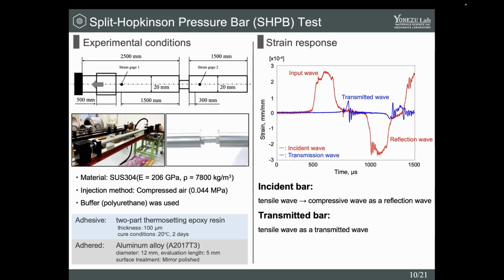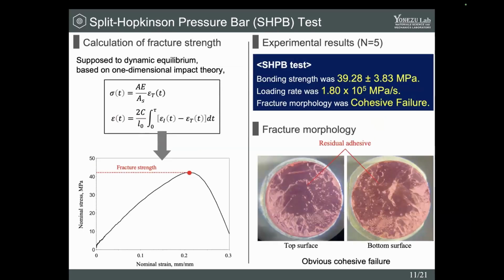This is an experimental example of the strain response sheets of incident and transmitted bars. If dynamic equilibrium was satisfied, the nominal stress and nominal strain of epoxy resin layer were calculated by these equations. As a result, bonding strength of SHPB was defined as about 40 megapascal, and fracture morphology was cohesive failure.